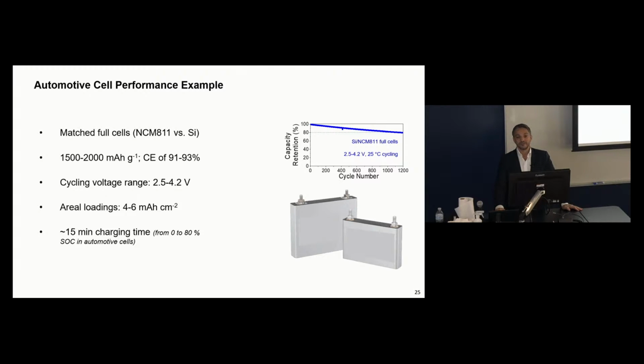If you have autonomous vehicles, the demand will be higher. So you probably would need something like 3,000 cycles to satisfy this demand, to have, let's say, a 1,000,000-mile battery. And it is all feasible. In automotive cells, the loading is typically higher. And another important parameter is that you have this energy density gain, right? You have higher performance, but you want to make sure it's not at the expense of something else. It's not at the expense of safety. It is not at the expense of fast charging.